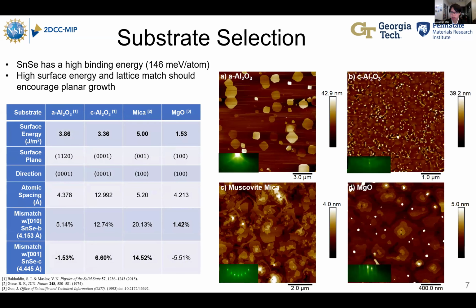Here are some examples of growths under the same conditions on each of these substrates. What we can see is that on both sapphires, the aluminas, we do have grain growth, but on A-plane sapphire it's not continuous across the surface. On C-plane sapphire, we do have continuous surface coverage, but we have a lot of out-of-plane growth. We can see in the RHEED patterns by the streaks or by these rings, and these rings indicate polycrystalline growth, which essentially means we have no predominant in-plane orientation, and we're growing outwards. So it's not exactly what we're looking for. In the mica and MgO, however, we do see these streaks. It's clearer on the MgO, where we see this predominant in-plane orientation along the 010 direction.